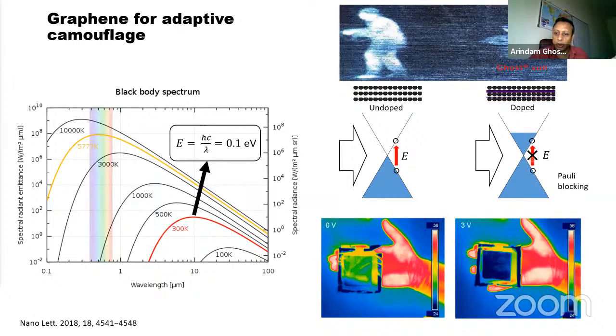But if I now dope it using graphene, electrostatically or chemically, then you can see the hand can no longer be seen. It has disappeared, it has vanished. That's because the infrared radiation emitted by the body can no longer penetrate through graphene and get re-emitted. So this is how graphene can be used for adaptive camouflage, and this is an interesting application of this unique band structure. So I wanted to give you this example.